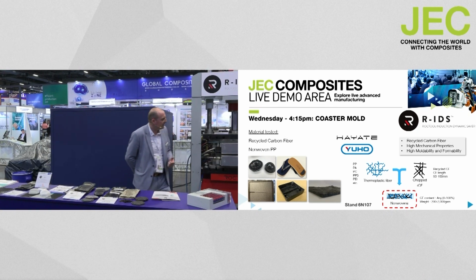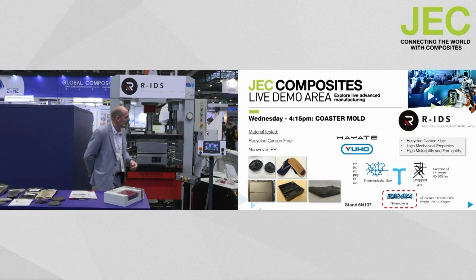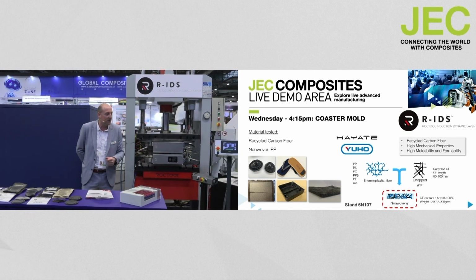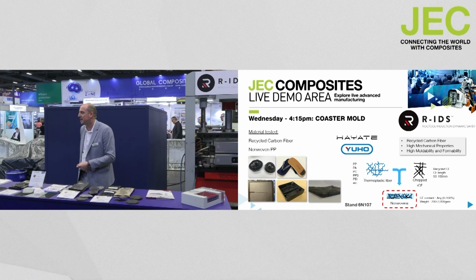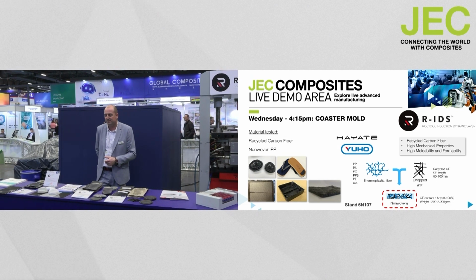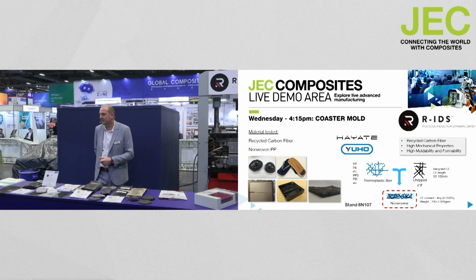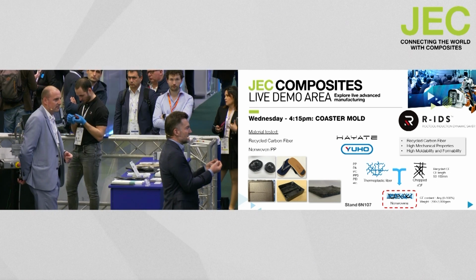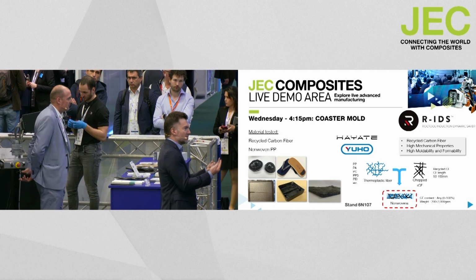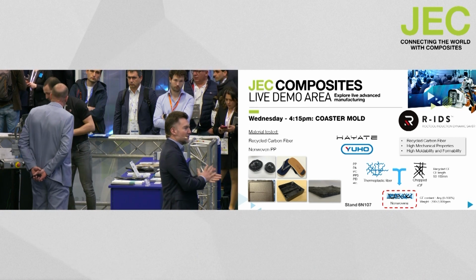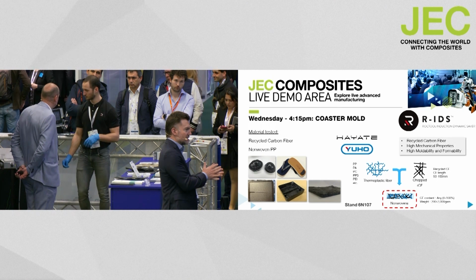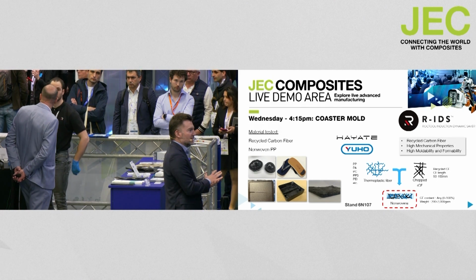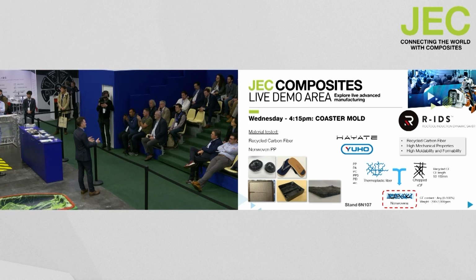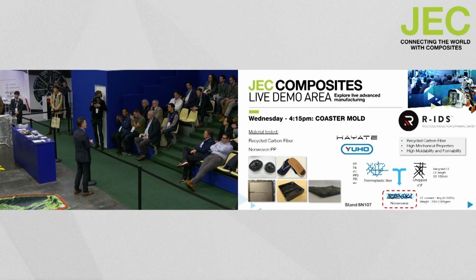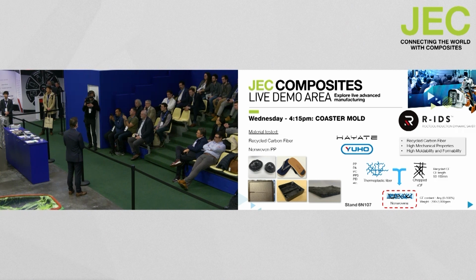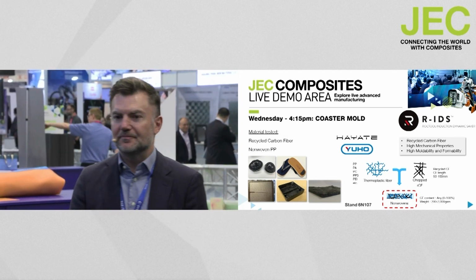So now I think we reach, again, 10 degrees before the demolding temperature, and as soon as we can, we open the mold. One thing: the time we open the press, with the high heat molding, the resin inside the material will migrate to the surface and we'll get this very nice surface finish. You'll be able to see that the resin covers all the fibers. That's a sign of a good consolidation, a sign of good resin flow. It means that the part is fully consolidated and there's no lack of temperature.